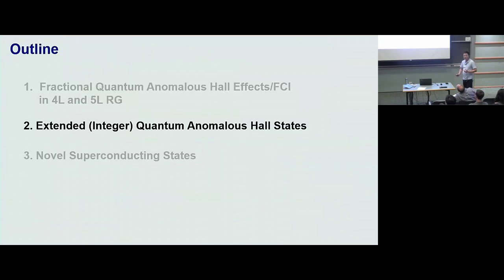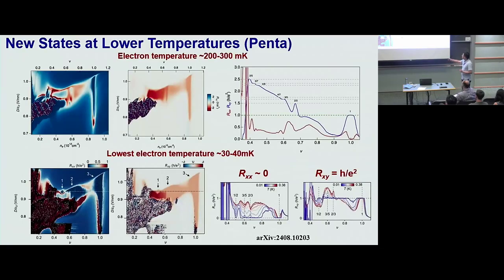Okay. Next, I'm going to show you something that's really unexpected. Again, this is our data, published last year, and this is about 300 millikelvin in electronic temperature. And you can see those fractional states, right? But if you really cool it down to the lowest temperature that we can access now, you get maps like this. It's the same device, okay? And we don't think there's any degradation because it's encapsulated. What you find is that, okay, you still have dips here that correspond to FCI, fractional fillings.